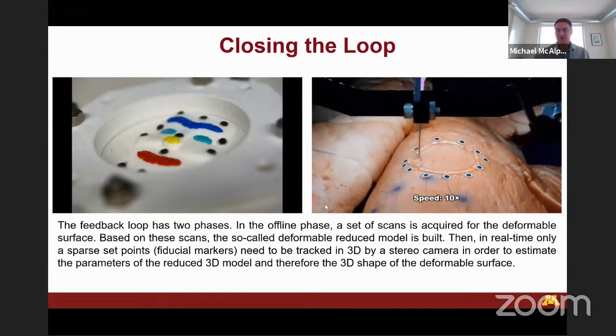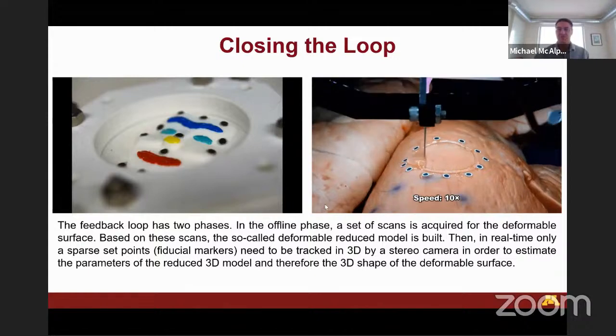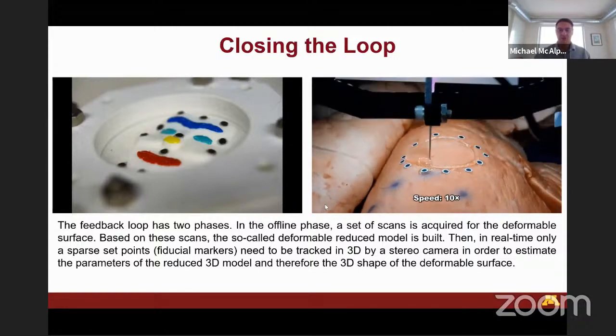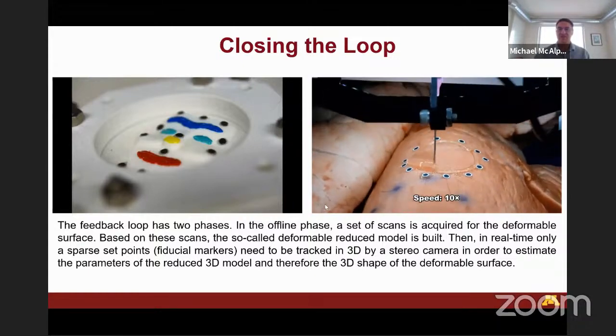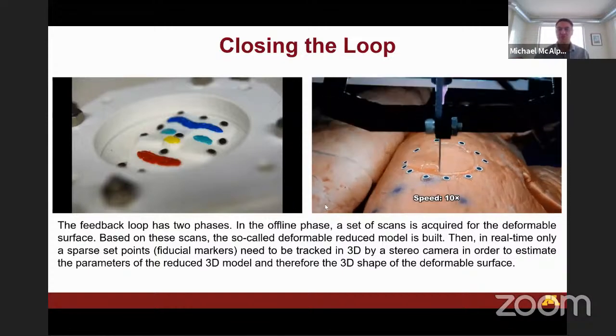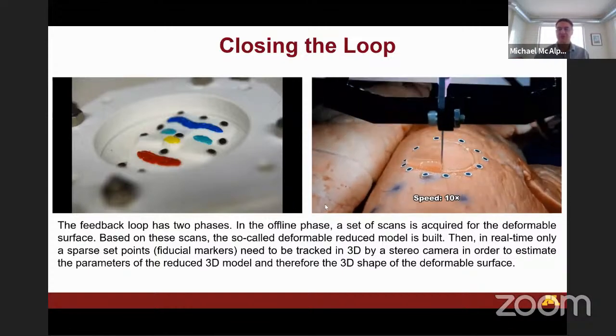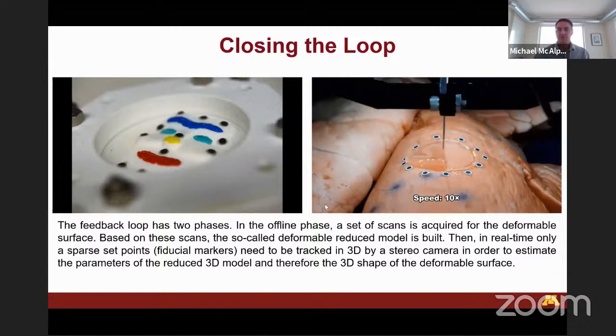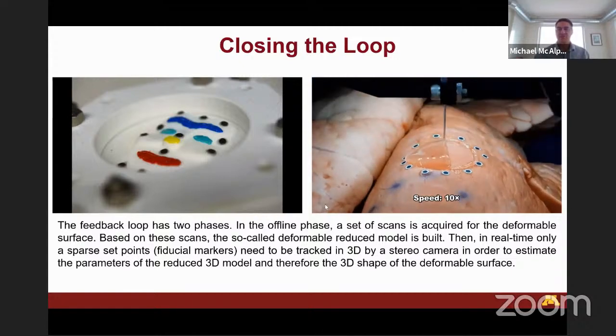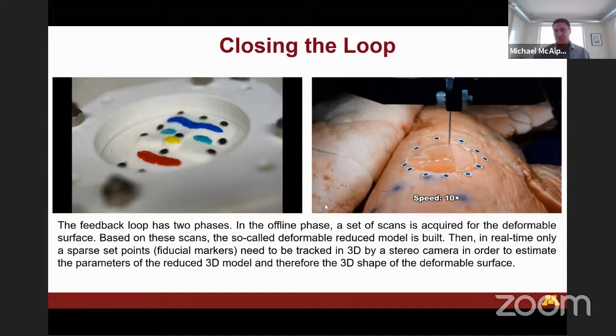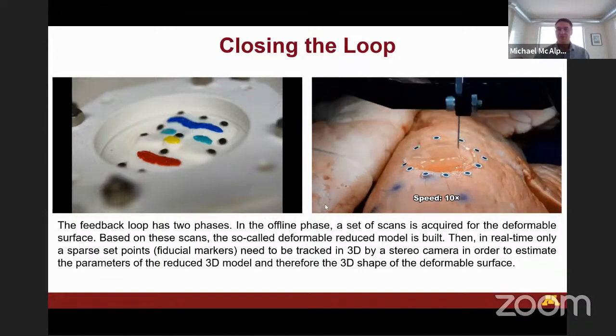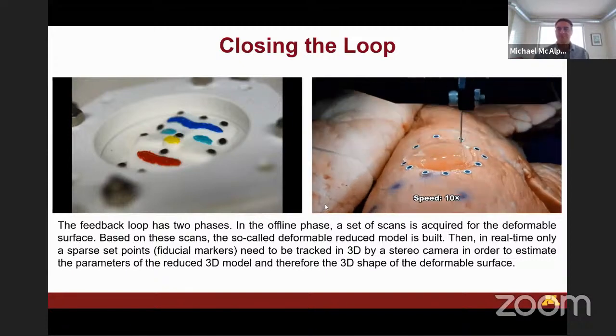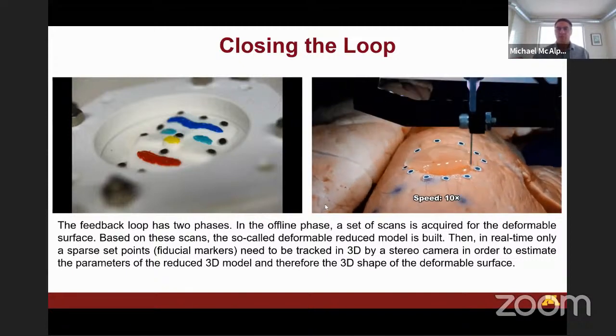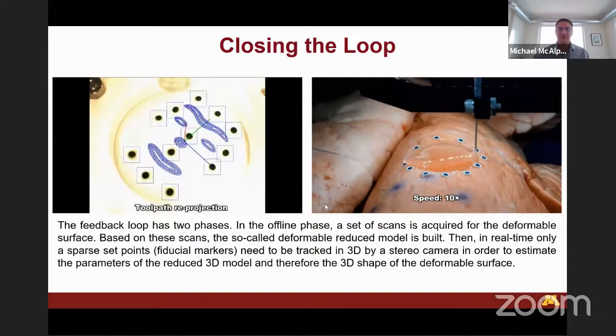Here we're actually printing an ionic hydrogel on a breathing lung surface by tracking this deformation. You can see there's only 12 fiducial markers there, but still we're able to do this tracking because of the offline process that we did first to print this ionic hydrogel directly on the surface of breathing lung tissue here. Okay. And once we cure that ionic hydrogel after printing, we can create a sensing structure.